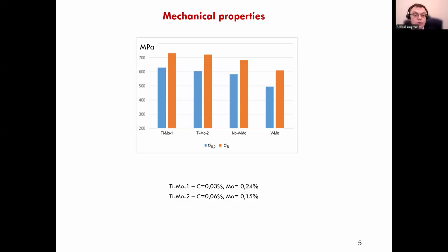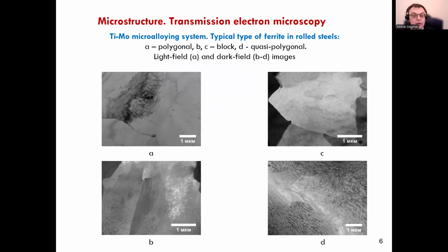To clarify the noted features of the behavior of mechanical properties, a study was carried out of structural state characteristics and the present phase precipitates in rolled steels. By means of transmission electron microscopy, it was found that all study samples have a ferrite microstructure. All samples of steels microalloyed with titanium and molybdenum have a ferritic microstructure, while samples of rolled steels of the vanadium molybdenum and niobium vanadium molybdenum microalloying systems have a ferrite pearlite structure. Apparently, due to ferritic microstructure, rolled titanium molybdenum steels were more ductile.